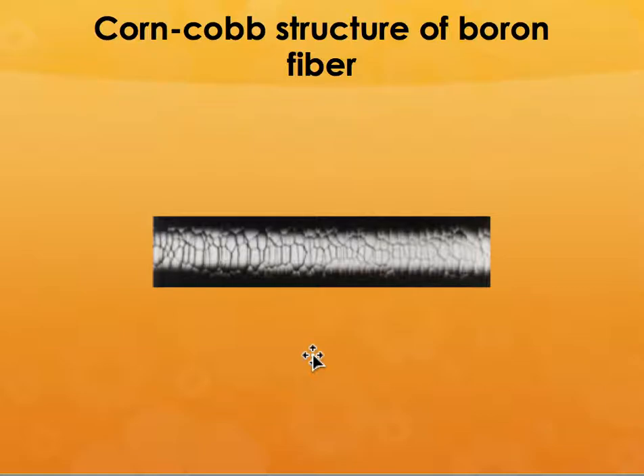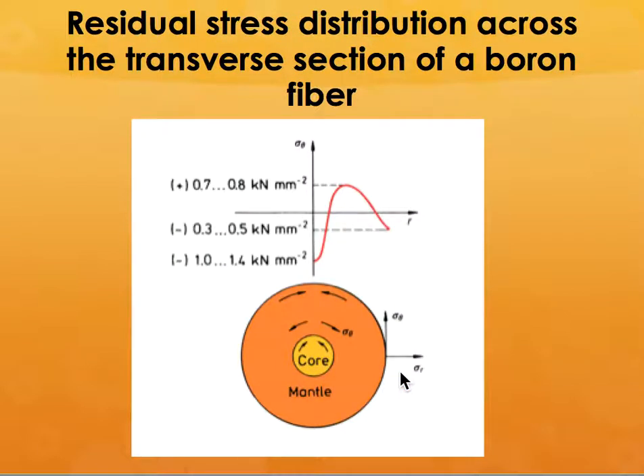If you look at it at very high magnifications, you can see that the boron fibers have what is called a corn cob type of structure. When the boron is depositing around the fibers, it does not deposit uniformly. First some part deposits and then more boron comes around it, so it tends to become a corn cob type of structure. When you deposit it, you're going to have different kinds of stresses around the fibers. So you are going to have some amount of residual stress across the transverse section of a boron fiber. In some cases, it is good, but in all cases, you try to reduce the residual stress as much as possible.